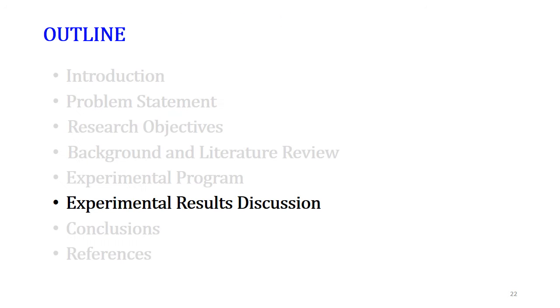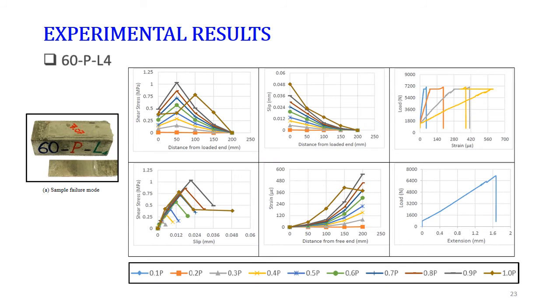So we test all, and I'm showing a sample of the results. Here is the typical result of one of the tested elements, which has a concrete strength of 60 megapascal. P is for plain concrete, and L4 means this is L number 4, which is the bonded length. L4 is basically the 200 millimeter, the largest length we have. And here the figure shows you the different behavior.